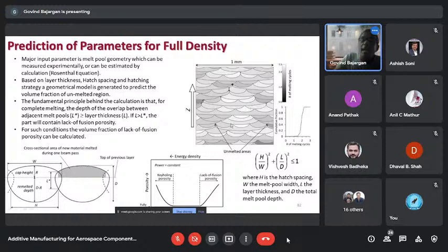With that, by changing the process parameter, from the equation we can find out what the dimensions of the melt pool are, and by changing the hatch spacing you can model it and predict where the unmelted zone will be and which condition will lead to a fully dense product. So these are very simple techniques people have used to resolve the issue of optimization, because it's a very complex task.